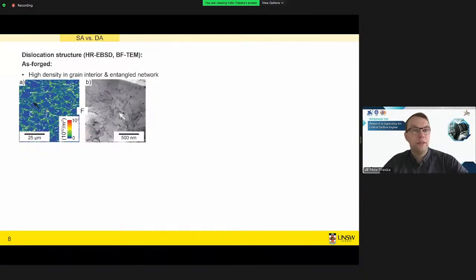Now we want to have a look into the dislocation density, and we have a look at the as-forged condition. So on the left-hand side, we see an EBSD map, but only reconstructing the geometrically necessary dislocations. You have to ignore all the grain boundaries. They just show up in green and yellow, but rather focus on the grain interior. I can get a laser pointer. So we're looking at these regions here, and we see that there are these dislocations progressing far into the grain interior. And we can confirm this with TEM imaging, like here on the right-hand side.